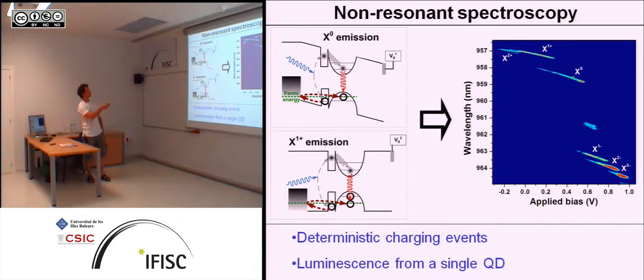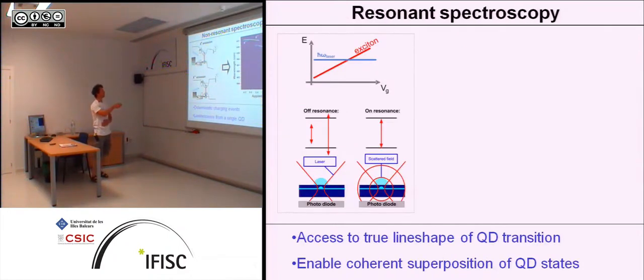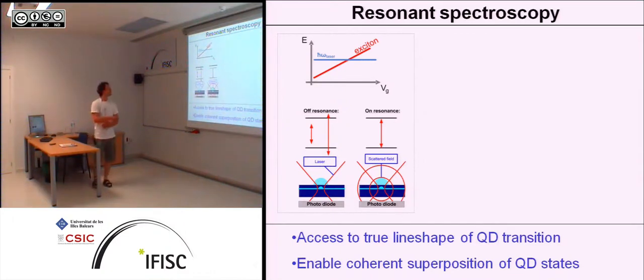But this is all non-resonant because you excite with high energy, and you have to have a relaxation process in here. So you cannot really coherently transmit information optically from outside the system to a quantum state, because you will lose a large amount of information in exactly that process. So the next step is to do resonance spectroscopy. And for that, we use a narrow linewidth laser, whose line is much narrower than the transition line of the exciton state in the quantum dot. And for example, we now leave the energy of the excitation laser constant, and we tune the exciton using this DC Stark effect I was showing before.